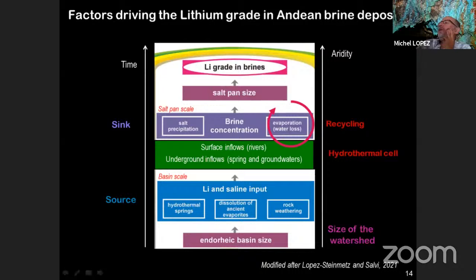So Lopez, Steinmetz, and Salvi proposed a general model for the factors driving the lithium grade in the Andean brine deposits, from the source and the size of the watershed. Lithium is mobilized by hydrothermal spring, dissolution of ancient evaporite and rock weathering, as we discussed before, at the basin scale. Then the lithium is transported by surface inflow, river and runoff, of course, and underground inflow associated with spring and groundwater, associated with hydrothermal cells, that lead to the recycling of the lithium close to the surface. This process of recycling by evaporative pumping leads to salt precipitation and lithium enrichment in the brine.